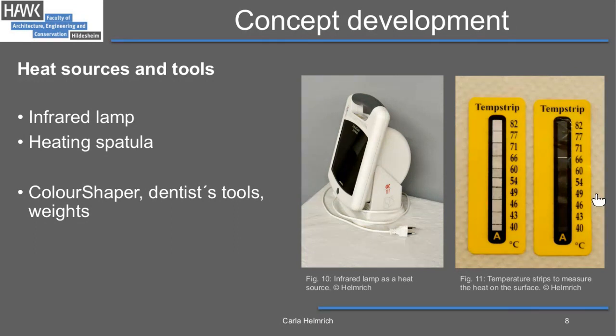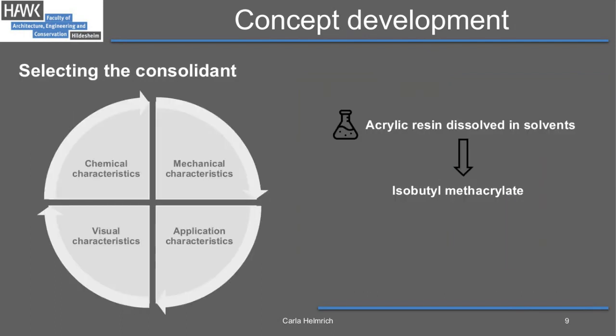However, laying down the blisters alone was not sufficient to ensure adequate adhesion to the carrier. For this reason, an additional consolidation agent had to be used. The consolidation agent had to be able to be used above all in combination with extreme heat. That is, it had to be thermoplastic. For this reason, it was decided on an acrylic, the isobutyl methacrylate in solvent. In order to determine the correct concentration of the agent, tests were carried out on the object.